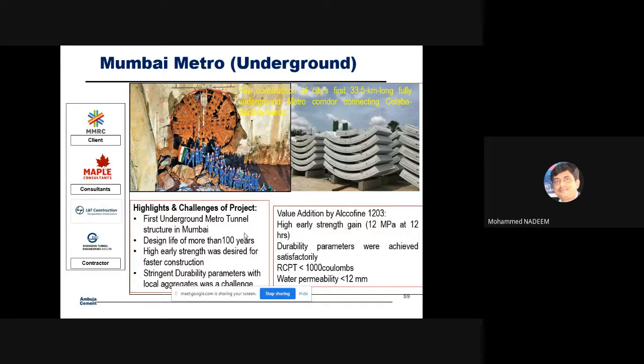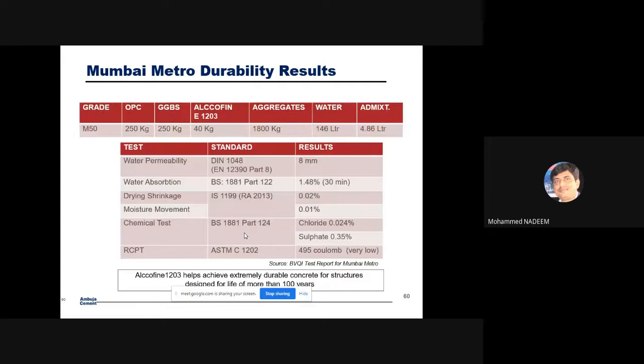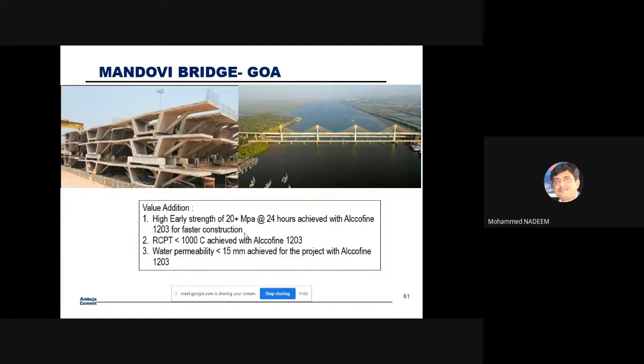There also we supported with a solution, and they were utilizing the ultrafine materials. These are the mixes and the results. Mandovi, Goa: again there is a bridge. These are the precast components in a very aggressive environment. They were looking for 20 MPa in 24 hours, RCPT less than 1000, and water permeability less than 15 mm. Nowadays all the durability requirements are being mentioned, and you have to give concrete satisfying the requirements in both the plastic stage and the hardened stage.